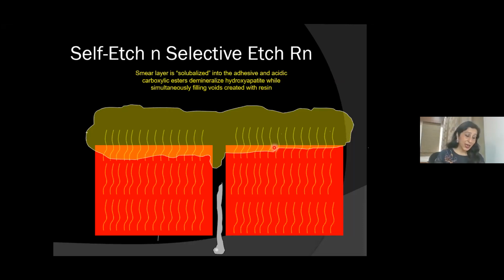Now is the time that the bonding agent is light cured. With an LED light preferably, which has a light intensity of more than 500 to 1200 milliwatts for 10 seconds. So this is the correct way of applying the bonding agent.